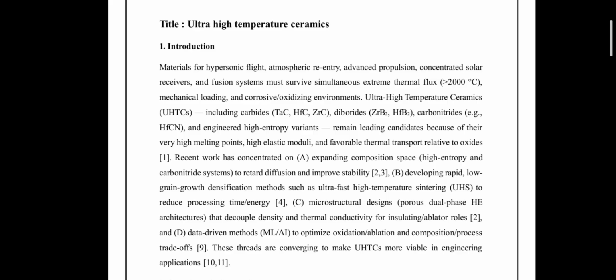Ultra high temperature ceramics, such as transition metal carbides like tantalum carbide, hafnium carbide, zirconium carbide, diborides like zirconium diboride and hafnium diboride, carbonitrides, and more recently, high entropy ultra high temperature ceramics, are leading candidates because they combine exceptionally high melting points, very high elastic moduli, and better thermal transport than oxide ceramics. This combination is rare. However, high melting point alone is not enough.